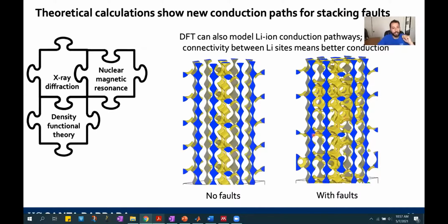So what we see here on the left is that we mostly have chains going up and down. And this is how lithium would really be moving through my material. But as I introduce the stacking faults, I create these loop features. And these loop features are increasing the connectivity between different lithium sites. And in that process of increasing the connectivity, we can start to get much better conduction through our structure.